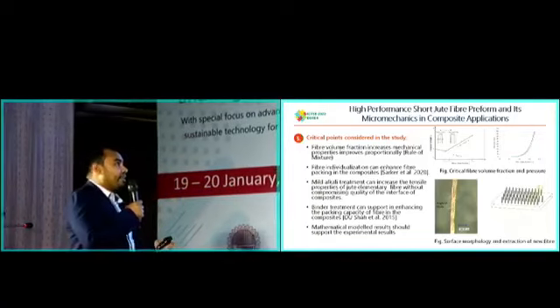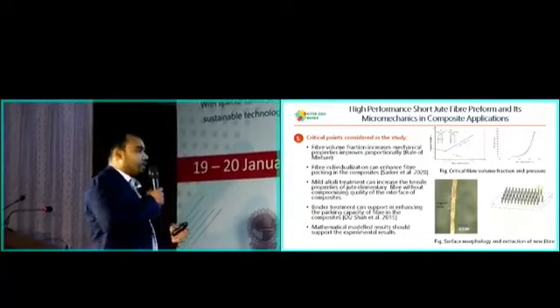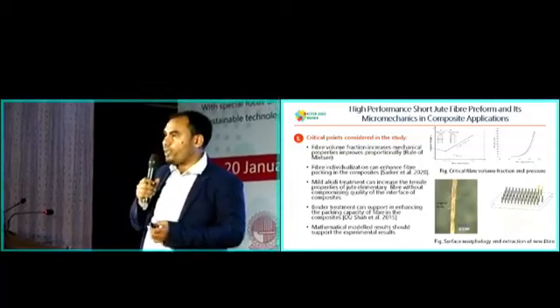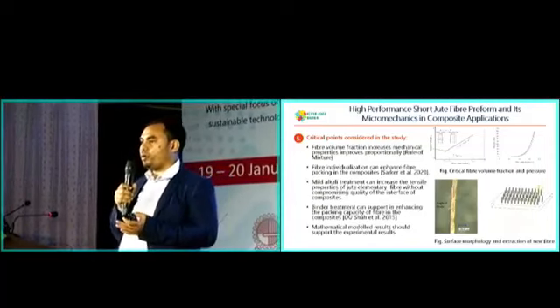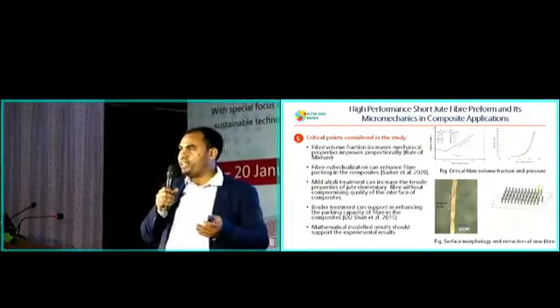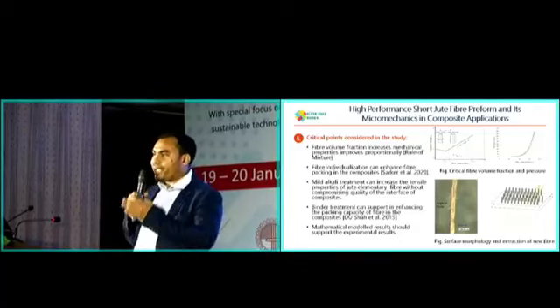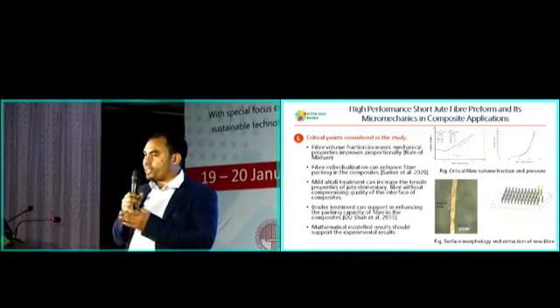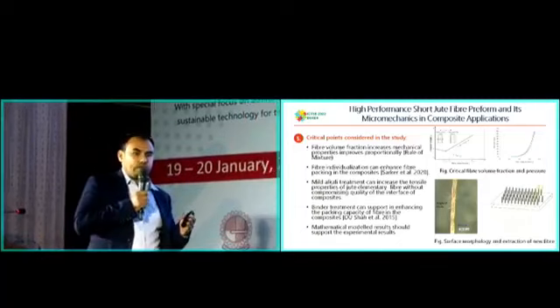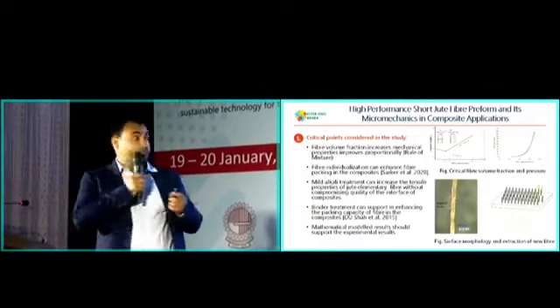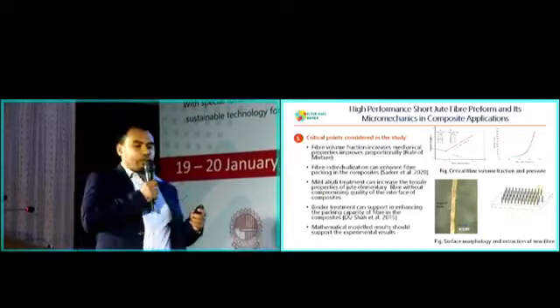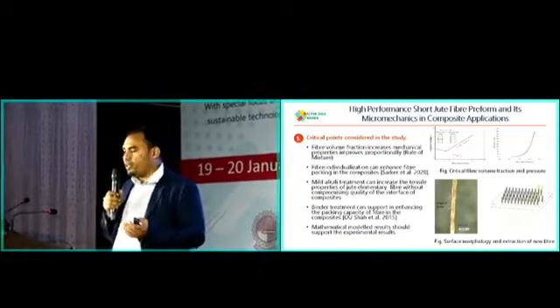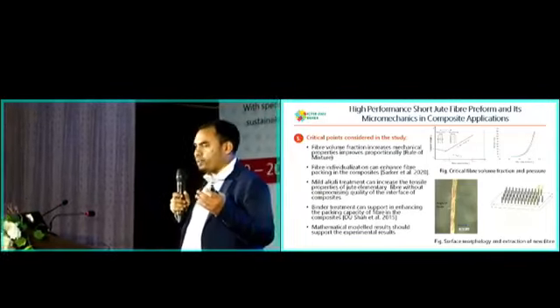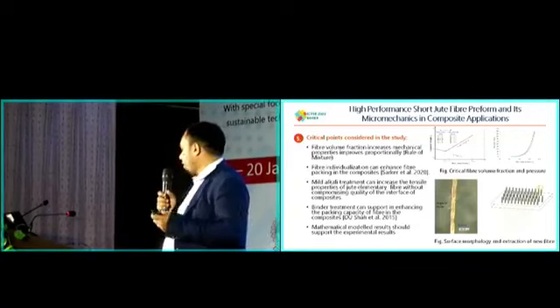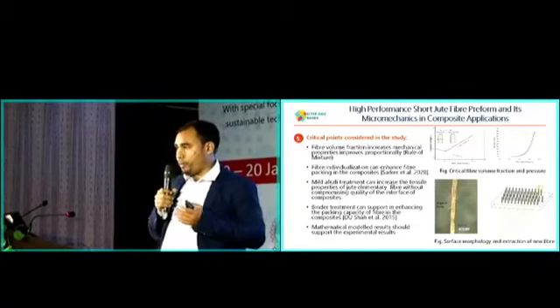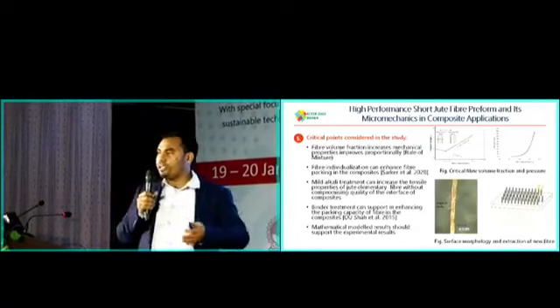After selecting the pressure, we went through the fiber morphology. The traditional fibers come with a lot of polysaccharides that increase the interfibrillar angle of the elementary fiber present in the technical fiber. So that needs to be taken into consideration. For that reason, in a recent study, we found that by separating the elementary fiber from the technical fiber, it is possible to get the maximum mechanical properties of the fiber because of the surface smoothness and also the uniformity of the fiber.